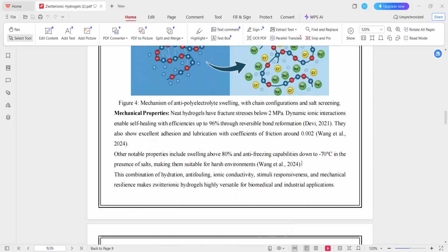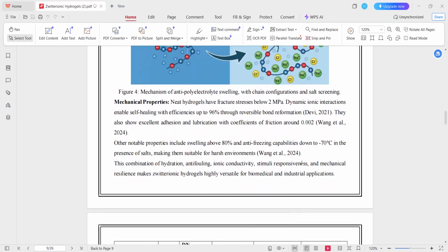Mechanical properties. Despite the excellent hydration, Zwitterionic hydrogels are often mechanically weak when used alone. Neat Zwitterionic hydrogels typically exhibit fracture stress below 2 megapascals. However, the presence of dynamic ionic interactions allows for self-healing behavior. When the hydrogel is damaged, reversible interactions such as metal-ligand coordination or ionic association break and then reform over time. This enables recovery of the mechanical strength, sometimes reaching more than 90% of the original strength within a day. In addition, Zwitterionic hydrogels show excellent lubrication properties with extremely low coefficients of friction, which is useful for joint lubrication and soft tissue interfaces.